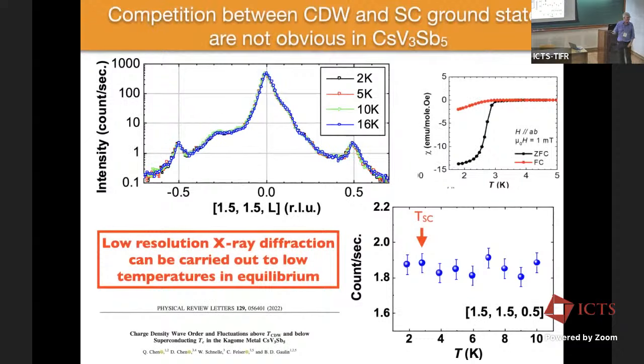Okay, and then the last result, and I'll try to wrap up relatively quickly, is that because we don't have a high heat load in our sample, we can go down to much lower temperatures. In this case, we went down to about 1.9 Kelvin. And so that's about here on the susceptibility measurement. So the diamagnetic response is pretty much fully formed. At that temperature, we're at 2/3 of TC, and so I'm just showing you these entire scans over this range of temperature, and over here I'm showing you peak intensities, sitting at one of these positions and counting with very high statistics. And you can see that our conclusion is that there's no change in the CDW at the 3% level as you go into the superconducting state, that's essentially fully formed.